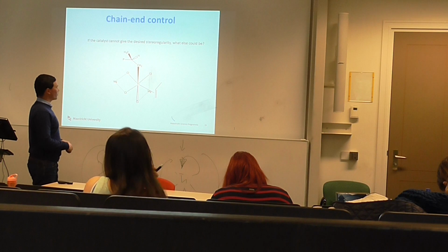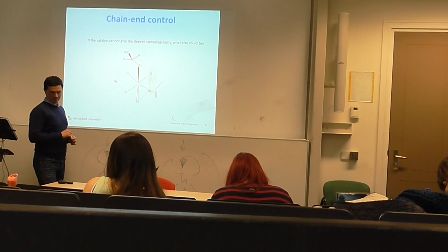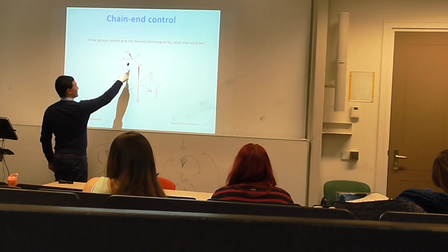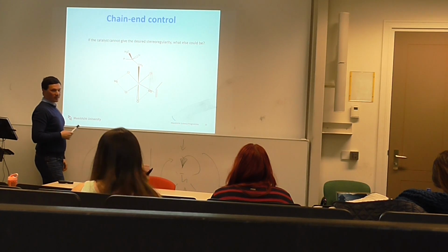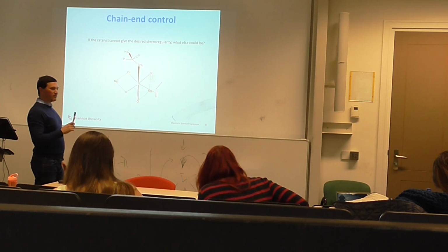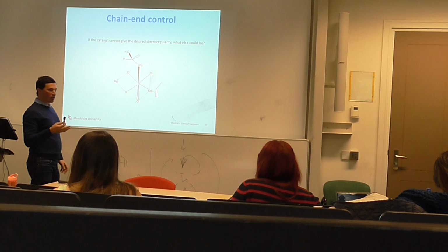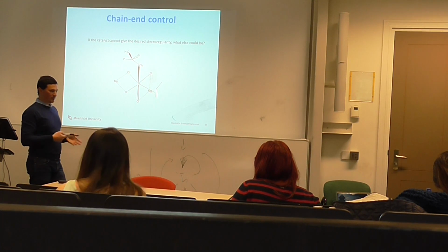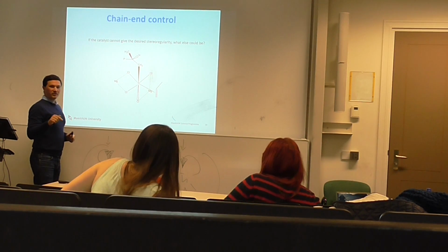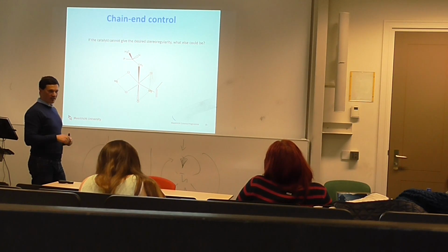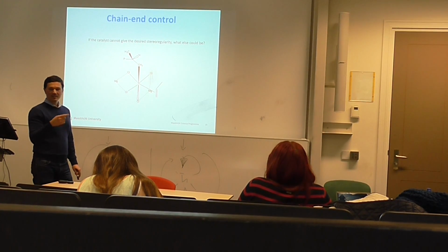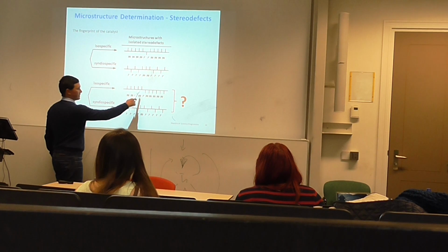What else is, where do you see a stereogenic point? Can you see? On the chain. On the chain. This is a chiral group, okay? So if your catalyst, sometimes depending on the catalyst structure, cannot give the right stereo selectivity, or let's say you are giving a lot of heat, we'll see this later, what can give stereo regularity is the chain itself, okay? So in that case, once a mistake occurs, instead of going back, it makes a mistake.